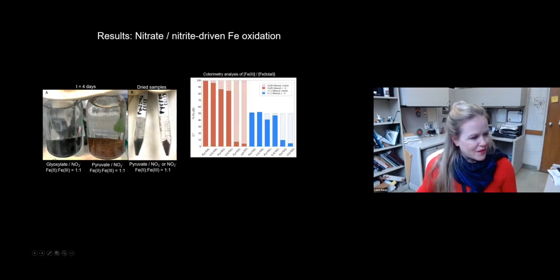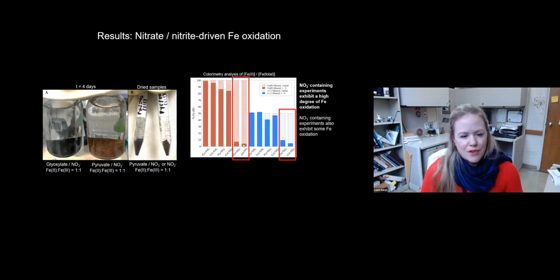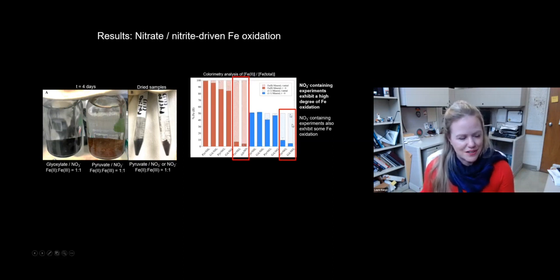And so this graph shows the percent Fe2 measured after the experiment. In this case, it's about 30 minutes after, so it's not even the whole 4 days. The shaded part shows how much Fe2 we initially put in, and then the solid part shows how much was detected after addition of the nitrate or nitrite. So we observe that nitrite-containing experiments exhibit a very high degree of iron oxidation, up to about 90-95% of the iron now oxidized, regardless of whether it is starting out at 100% Fe2 or 50% Fe2.